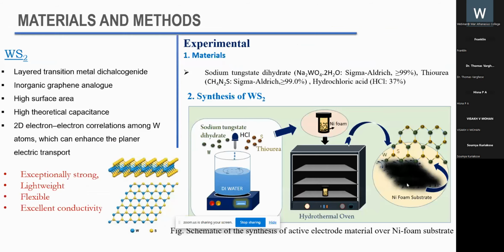The material we chose is 2D WS2 because it has higher theoretical capacitance and high surface area, it is an analog of graphene, and it has 2D electron-electron correlation among W atoms, which can enhance planar electric transport. These are the materials used for the synthesis of WS2, and a hydrothermal method was adopted for the commercial mass loading of 2D WS2. This is the schematic picture.